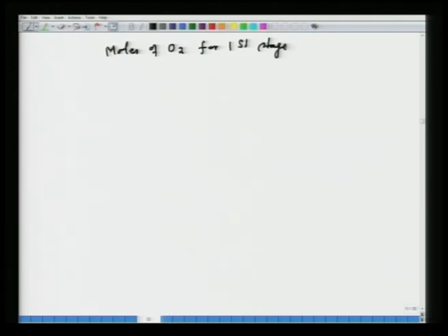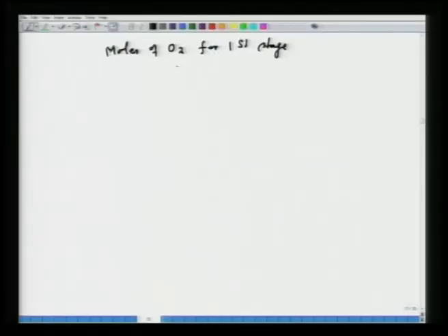You have to calculate all the amount of FeS coming from all sources, plus the Cu2S which is being oxidized to CuO. The best way to calculate the amount of CuO oxidized is from the percentage CuO in the slag. So you know how much oxygen is required for that purpose. So, moles of oxygen for the first stage will be equal to 226.34 kg moles.